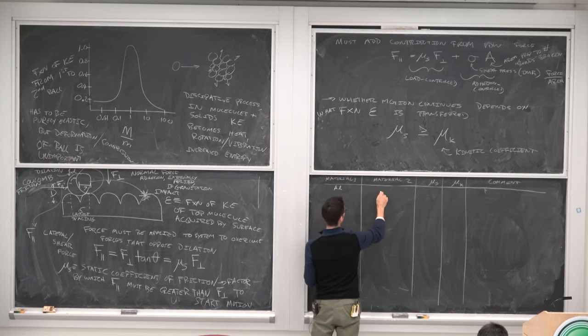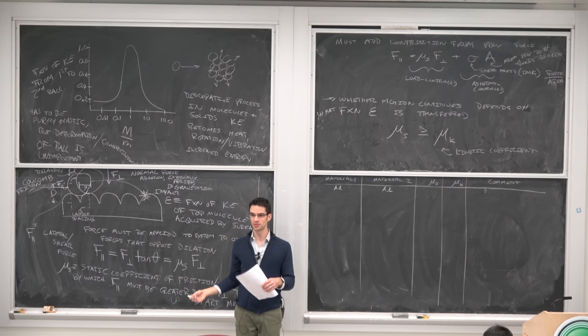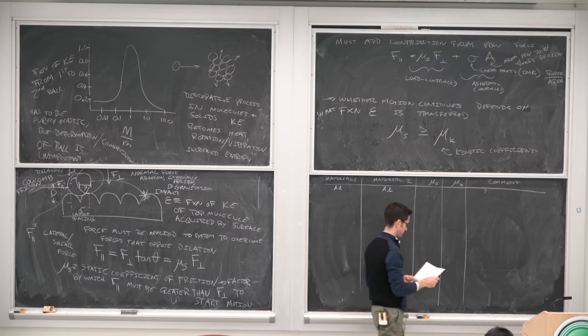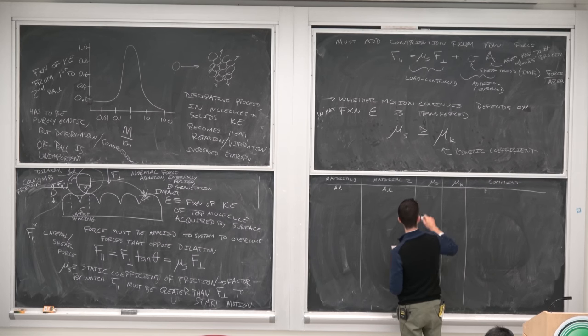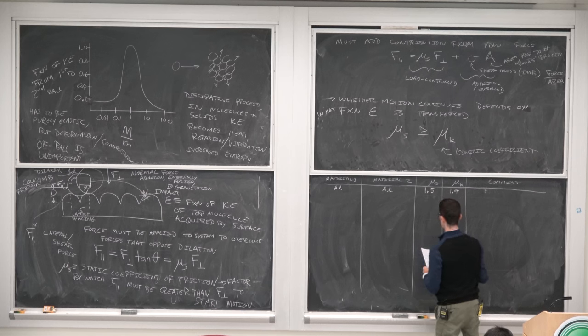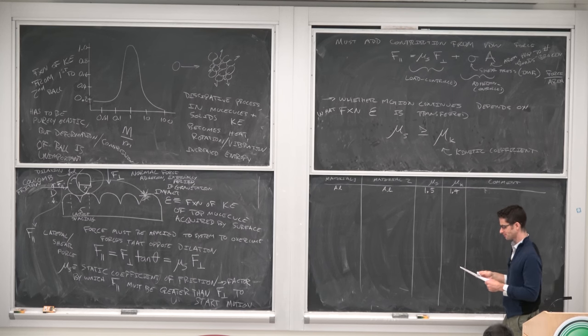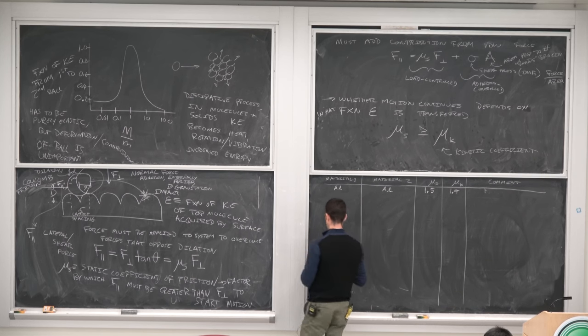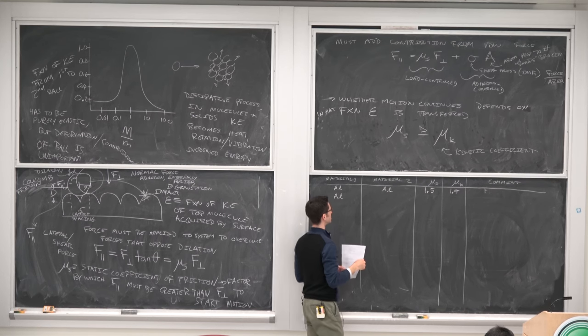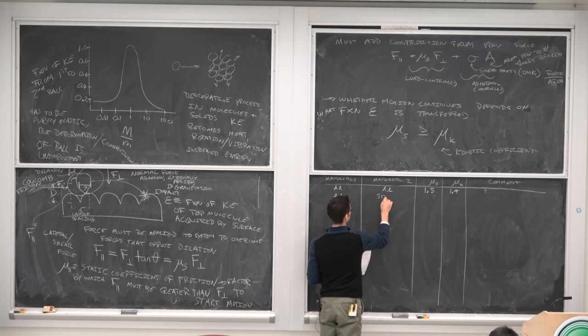How about aluminum interacting with aluminum? So take two aluminum solid blocks and you slide them past each other. Coefficient of static friction, 1.5. Coefficient of kinetic friction, almost the same, 1.4. Now, by way of comparison, before we comment, let's look at aluminum now interacting with steel.